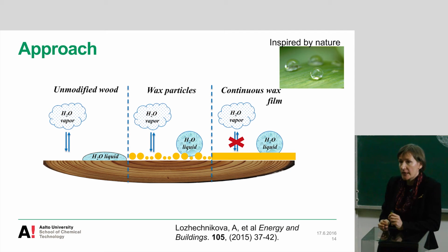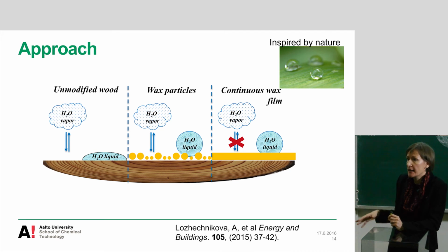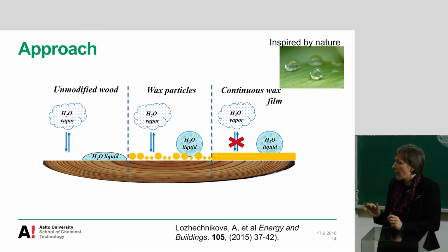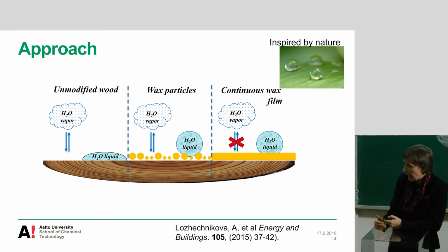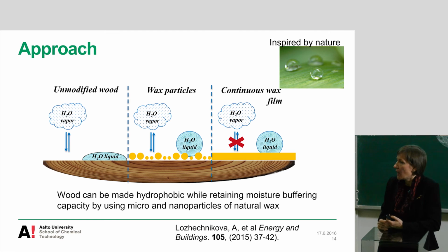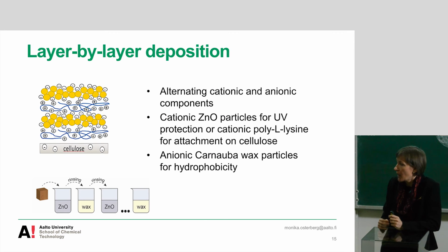But we thought that if we are adding particles, then it's non-continuous, and then the air can pass and the vapor can pass through, but it's still enough to give the hydrophobicity. And indeed, we succeeded with this. So we were able to make a hydrophobic wood surface that is still moisture buffering by using these micro and nanoparticles of natural wax. Then we continued this research by using layer-by-layer deposition.